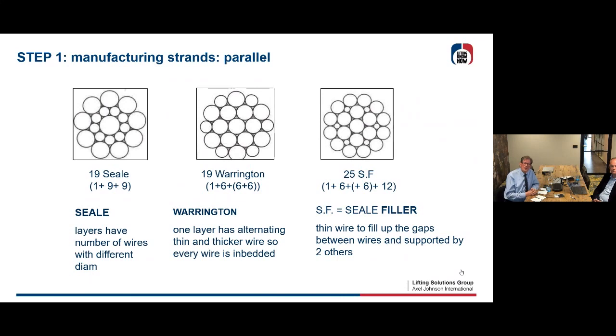The first one is called Seale, and it was invented by Mr. Seale, Tom Seale. You start with the inner wire and you surround it with nine little wires in diameter, and then you seal it up with 9 bigger wires at the outer layer. So this is a 1 + 9 + 9 Seale construction. The advantage is that it's very flexible. You have the parallel construction, so no point-to-point contacts, and you have a very big wire on the outside, so you can have a very abrasion-resistant strand.